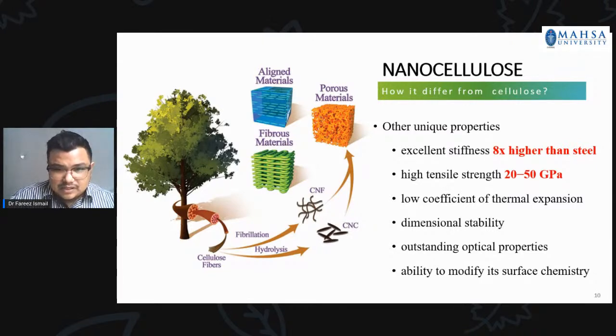And next, it has a low coefficient of thermal expansion, because nanocellulose has a crystalline structure that results in a lower thermal expansion coefficient, because the crystal structure of the NC is extremely uniform and structurally sound. Like diamond, it has the lowest known thermal expansion coefficient of all naturally occurring materials, and it shows that this material has stronger intermolecular bonds, and therefore a high melting point. This is the reason why you need high vibrational energy to break these bonds. And next would be dimensional stability.